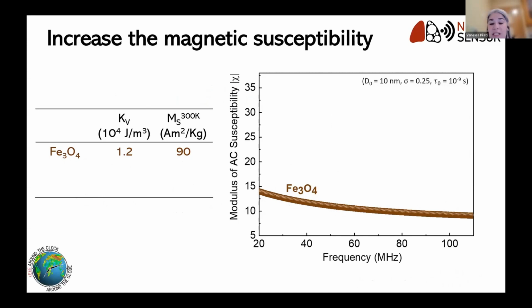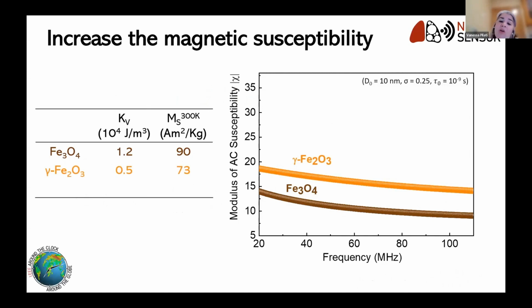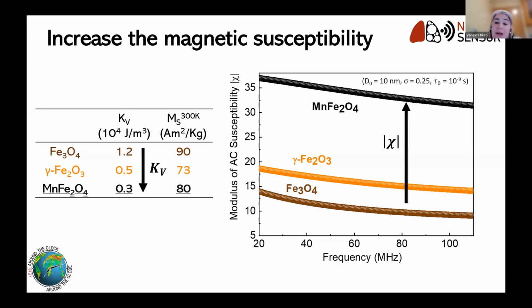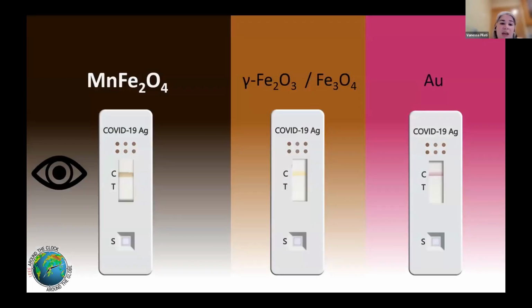We can see how this susceptibility, this is the modulus, can be modified. If we oxidize the nanoparticles, the magnetite, to obtain maghemite nanoparticles, therefore reducing their magnetic anisotropy, we will achieve a high value of the modulus of the susceptibility. But if we reduce it even more by changing the chemical composition of these nanotags, we can increase the susceptibility even more, and therefore we can increase the sensitivity for inductive detection. Another advantage of using manganese ferrite nanoparticles is that their colloidal dispersions are black or dark brown, while the magnetite and maghemite dispersions are more orange, and the gold ones, which are not magnetic, of course, are red.